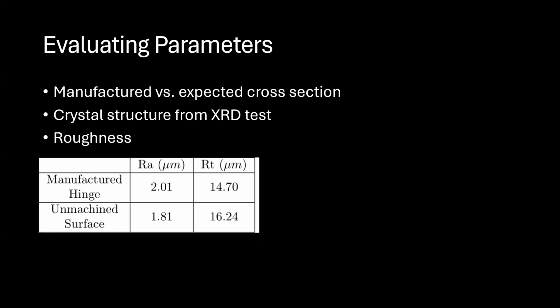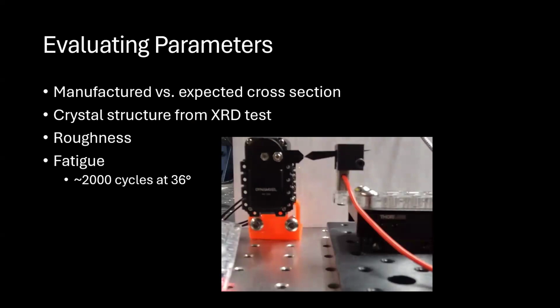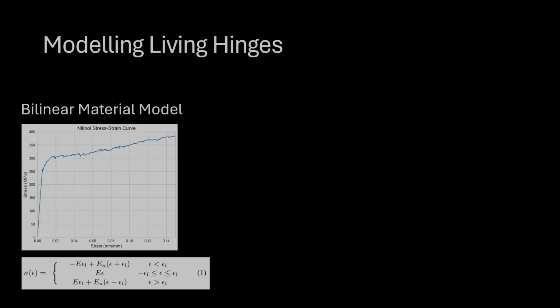We then measured the roughness using our confocal microscope and found that the roughness of the manufactured nitinol is not significantly increased from the bulk material. Finally, we performed a fatigue test on our nitinol hinges and found they performed similarly to previous works.